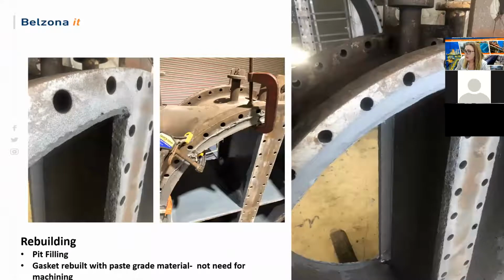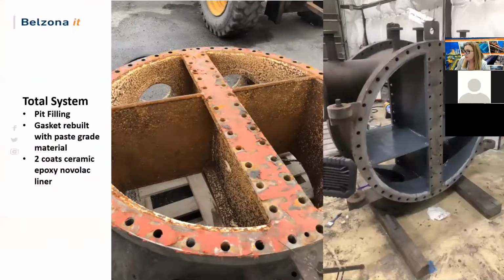Here's an example of rebuilding a gasket surface. This saves you from having to do any machining. All of this is done by molding. Another example on a channel head where, after blasting, we did pit filling on the internals. Then we remolded the gasket surface, again with no machining necessary. Then we applied 2 coats of a ceramic epoxy Novolac liner.